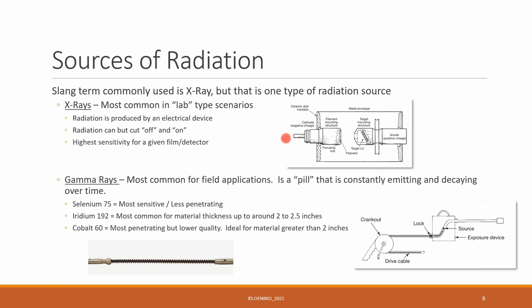So the function of x-rays and how they're produced, it's artificially produced radiation. So this is an overview of a basic x-ray tube. How it works is you send electricity in, electrons flow across through this vacuum tube, interact with a target material. It's a very high-dense material. And then there's a term, bremsstrahlung, you don't necessarily need to remember that, that occurs when those electrons hit, it creates the radiation. This is angled down so the radiation is angled down to the bottom in this particular scenario. Two of the primary benefits of x-rays is one, it can be cut on and cut off. So it's not constantly emitted. It's cut on by a switch, cut off by a switch. Also, for a given film or a given detector state, x-radiation is generally going to give you the highest sensitivity compared to the other radiation sources.